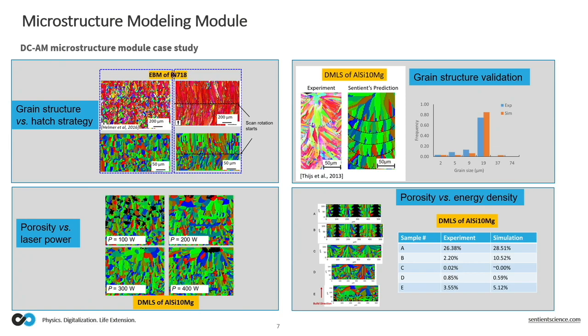The first one here on the top left corner, I want to show the flexibility of our model to input parameters that are set by the user. So I'm showing the comparison of our prediction versus the experimental EBSD for the Inconel 718. The people in that literature who did that experimental work used the same powder, but two different sets of parameters on the machine, and as you can see, the microstructure significantly changed because of those different parameters. And in the lower row, I did the same thing: I use the same material properties, but I changed my process parameters, and as you can see, the microstructure that we are predicting behaves differently, very similar to what is seen under, again, EBSD.